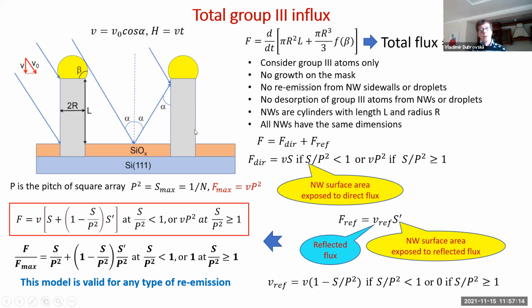So the nanowires will be considered as cylinders with radius r and length L, and beta is the contact angle, and f is the known geometrical function relating the droplet volume to the radius of its base. So we consider group 3 in the model, group 3 atoms only, no growth on the mask, no re-emission from nanowire sidewalls or droplets, no desorption of group 3 atoms from nanowires or droplets. And we also consider that all nanowires in the array have the same dimensions.